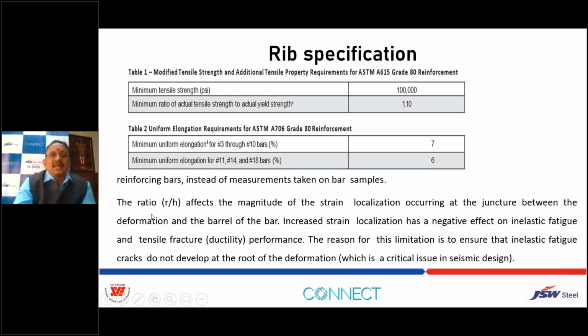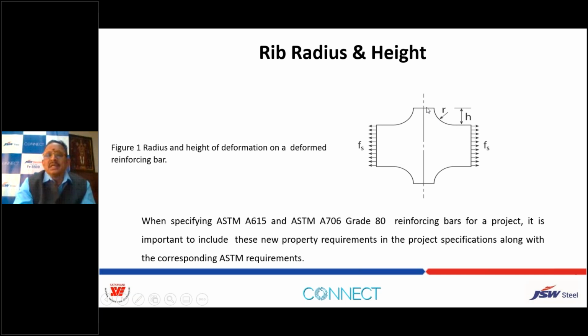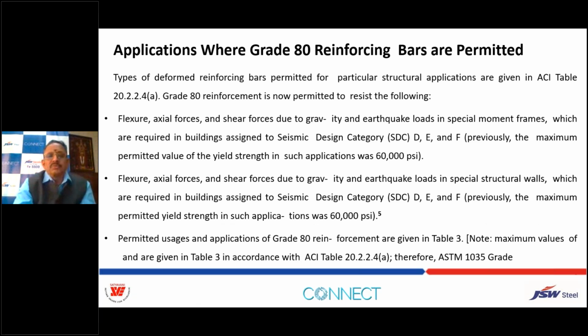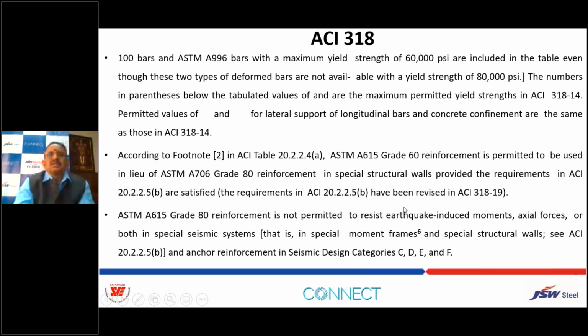So R by H affects the magnitude of strain localization. This is about the ribs. So here, this is the magnified view of the rebar. You can see the radius of the corner, root thickness and then height of the rib. So these are also defined for these bars as per ASTM and ACI codes. So we can use this grade 80 reinforcement bars with the proper calculations and modification factors and reduction factors. So you can see